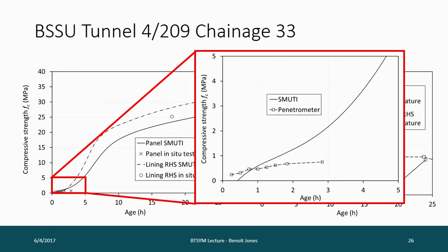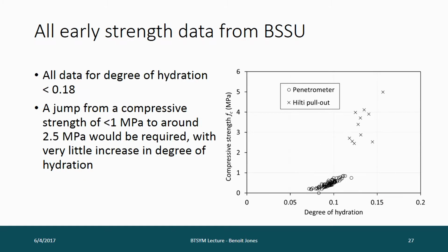But really, I think you can ignore most of the later ones. And I'll show the next slide, which proves why to some degree. If you plot all the data of strength against degree of hydration, you see that those later penetrometer results would have to jump from below 1 MPa up to about 2.5 with no increase in degree of hydration or time, and when you get the first Hilti pull-out tests. So it doesn't really make sense. So I'm pretty sure we've got a lot of problems with the penetrometer, really, so that is the answer.